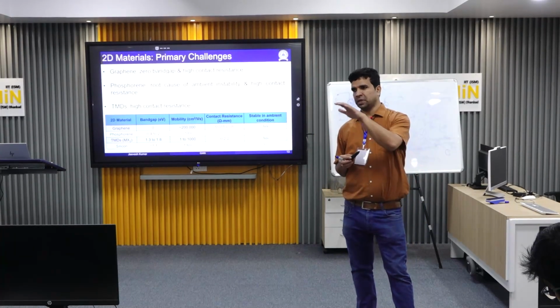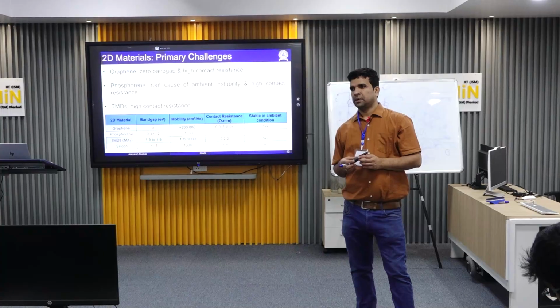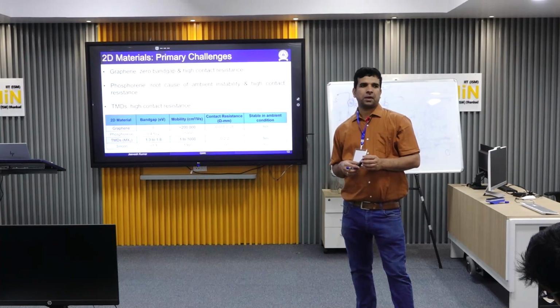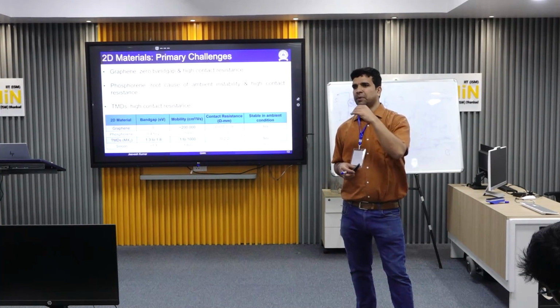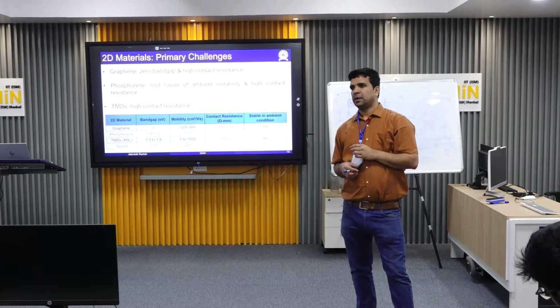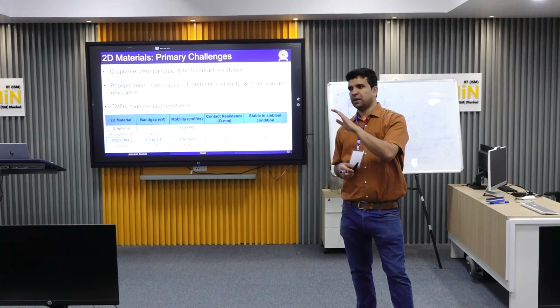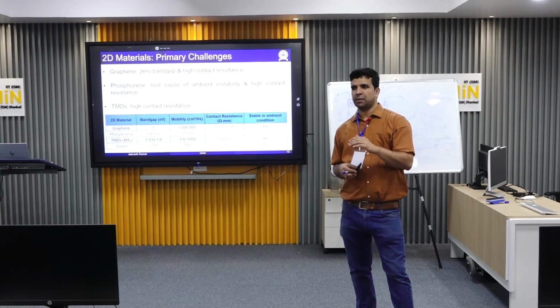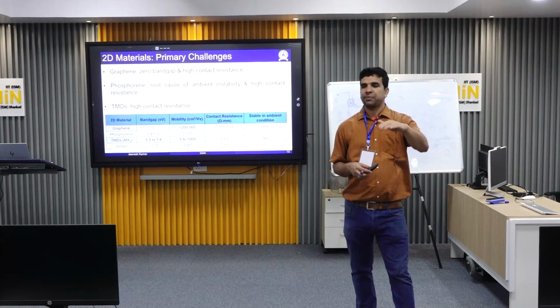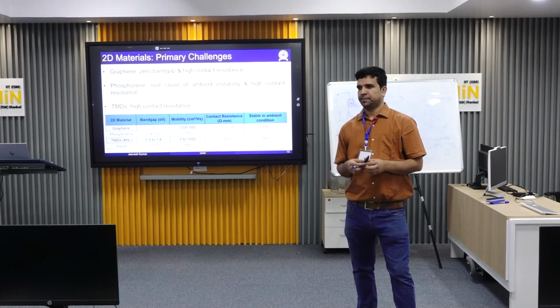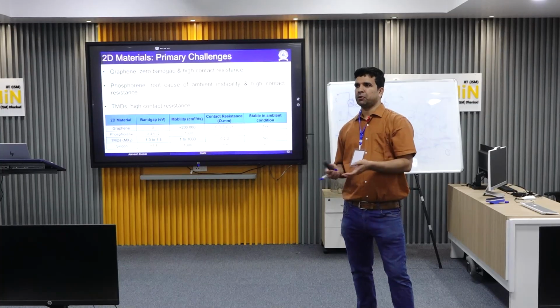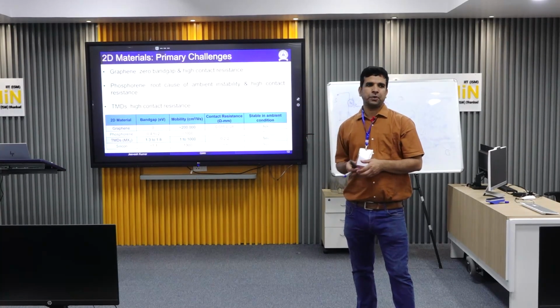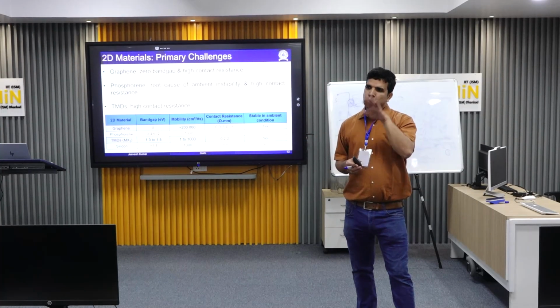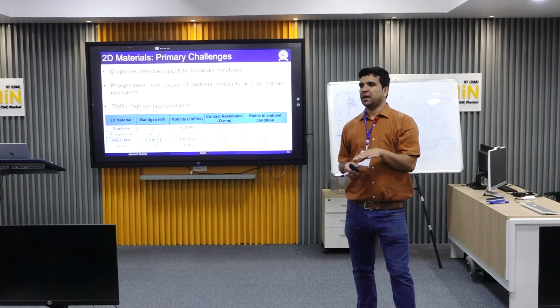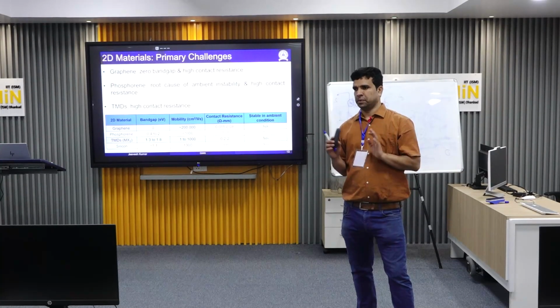Chemically also, it's not easy to open the band gap in graphene. But some people may claim that you put oxygen plasma and get a band gap. Actually, it's not graphene, it's basically graphitic oxide. They are converting graphene to graphitic oxide. It's a different material. It's not graphene. When you convert to a different material, you can make a band gap. But preserving the properties of graphene and also having a band gap, nobody has achieved yet, as far as I know.